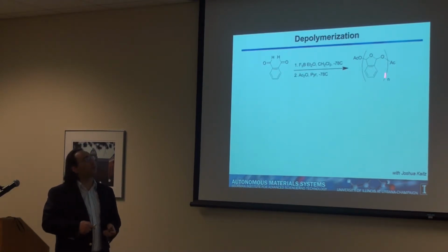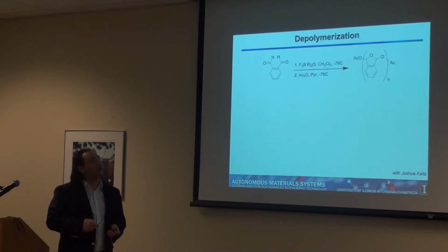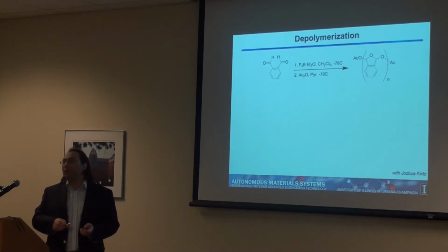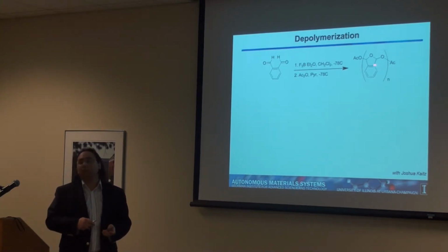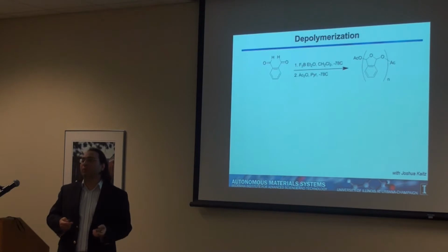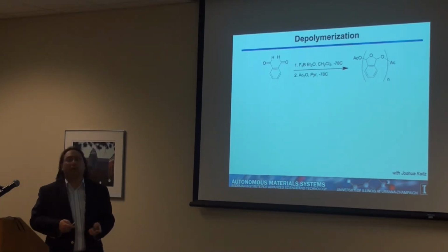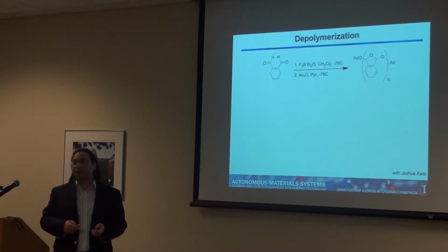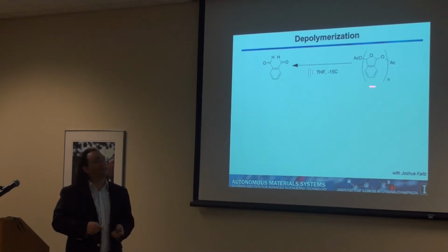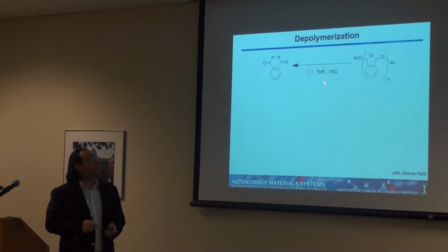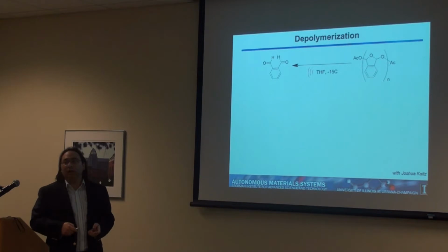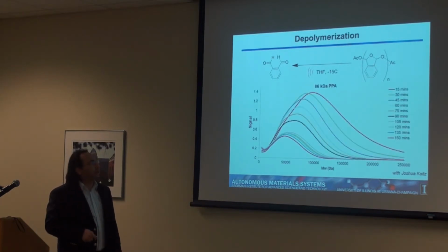The thing is, we were thinking, maybe I don't need the acid at all. If I break any bond in the chain, it's going to depolymerize. Maybe I don't need the mechanoacid at all. And we decided to study that. So basically, we take this polymer in solution, we apply mechanical force using high energy ultrasound, and indeed,